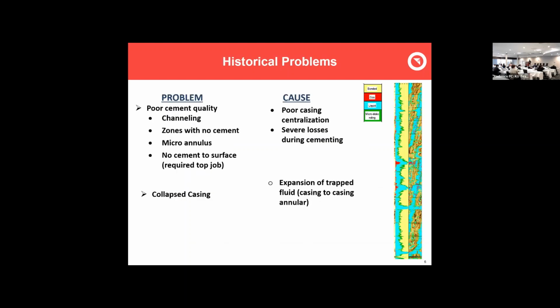Now, historically, some of the problems we've had with our cement jobs is really poor cement quality. So channeling, also losses of cement. A lot of times we're in fractured rock and we simply can't get enough cement to surface. A lot of times we have losses throughout the job. Some of the channeling I have here is caused by poor casing centralization. So a lot of times we really just minimize our deviation in the wells now.